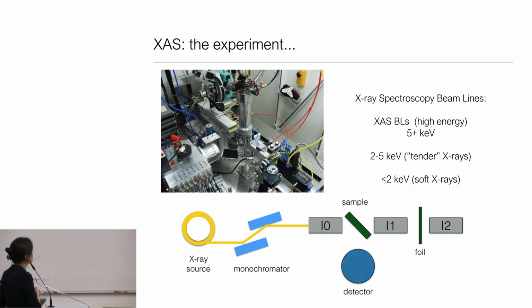And we need to then actually get those X-rays to the energy that we want. So we typically use a double crystal monochromator where the angle at which the X-rays come, using Bragg's law, selects for a specific energy. So we're selecting the incident energy using an optic. We then use typically gas-filled ionization chambers to measure the intensity before the sample and to measure the intensity after the sample. So in the simplest experiment, this basically just follows Beer's law. It's just a simple log of I0 over I1 type measurement.